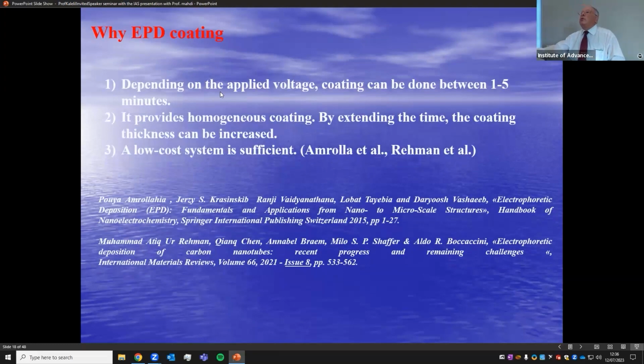So you see why EPD coating? Why electrophoretic deposition? Because you apply voltage, and the coating can be done between 1 and 5 minutes, or 10 minutes for multiple. And it provides a homogeneous coating surface. By changing the time, the coating thickness can be variable. And it's low cost. You can see some papers here.